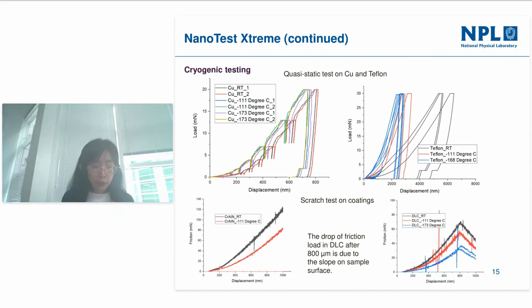And we also carried out some scratch tests, which show that with reducing temperature for the two types of coatings, the friction coefficient reduces, and by post-mortem examination of the scratch paths, we see improved wear resistance at lower temperature. And you can see on the right side for the DLC coating after 800 micron, the friction coefficient drops. This is due to the slope on the sample surface.